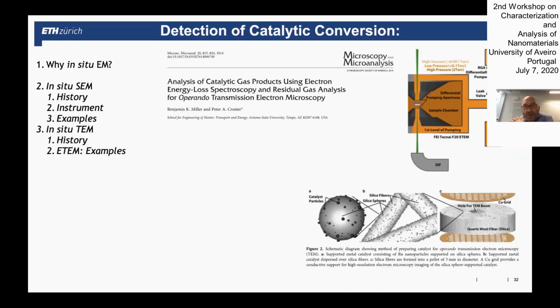They also used an environmental TEM, and they made use of the electron beam as a probe also to characterize and measure the chemical composition of the gas phase. So they have actually concentrated, packed a lot of catalyst. In this case, it was ruthenium nanoparticles on some silica fibers. They had a foamy structure of the silica fibers and impregnated this with ruthenium nanoparticles.